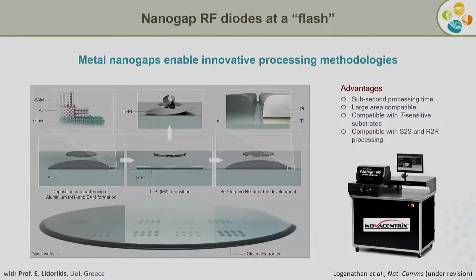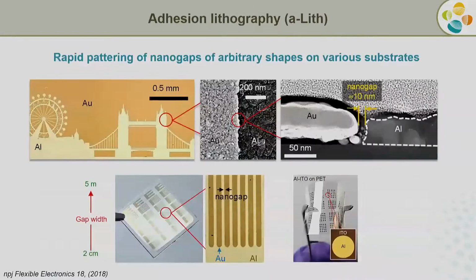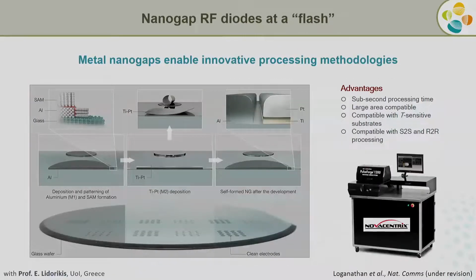Another way we have found to utilize even more energy efficient manufacturing technologies is to combine these nanogaps, essentially the same structure shown here, and place inside there a precursor material, not a semiconductor, but a precursor which is easy to process. We have water soluble precursors, so very environmentally friendly, unlike silicon that you need to grow with sophisticated methods. We can place it there and then take a big flash lamp, exactly the same technology we use for flash photography. And this is the machine we have. You flash the whole structure, a millisecond of intense pulse of light.